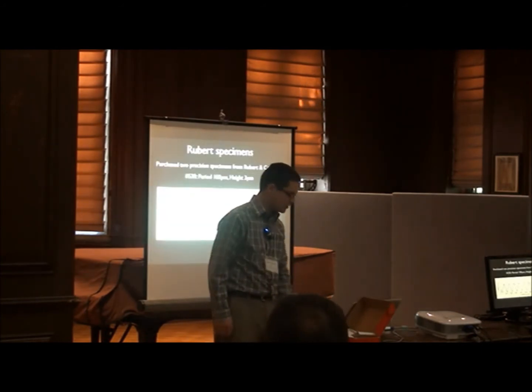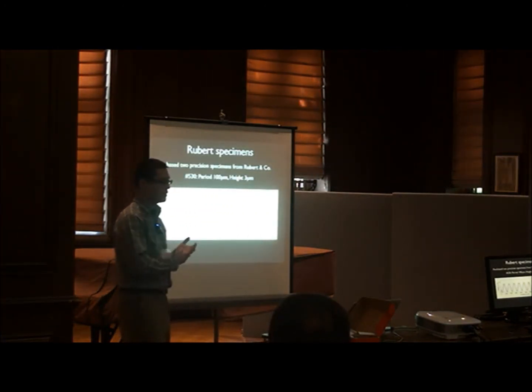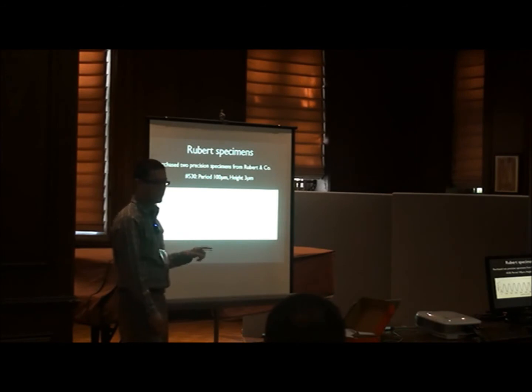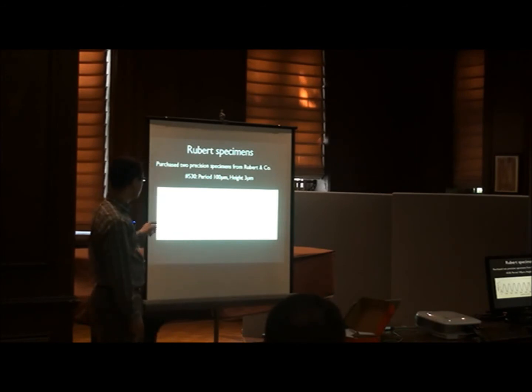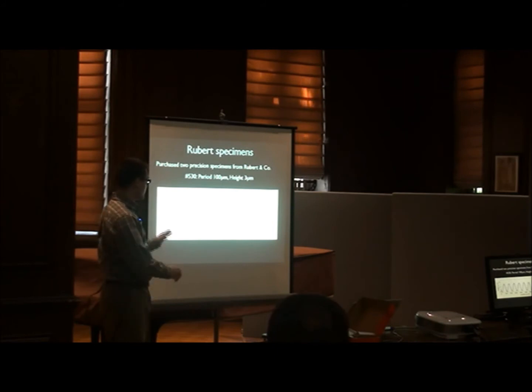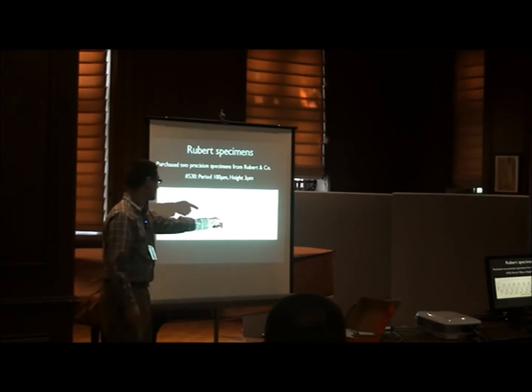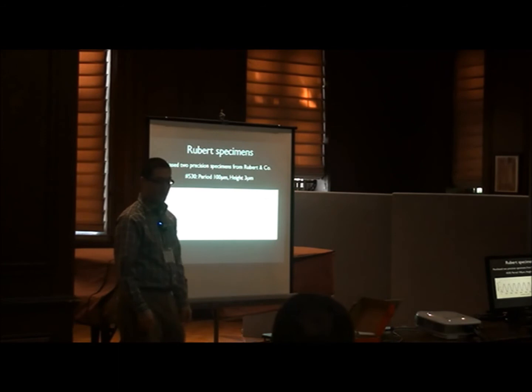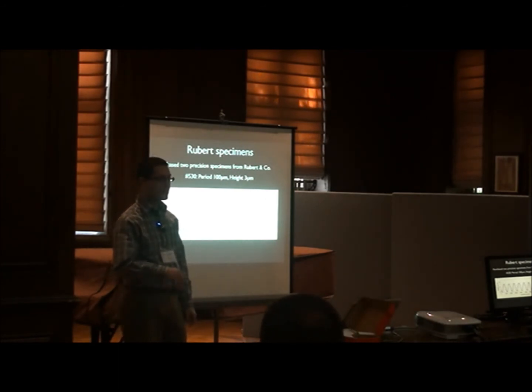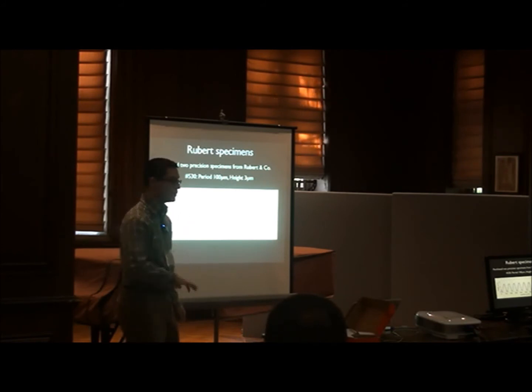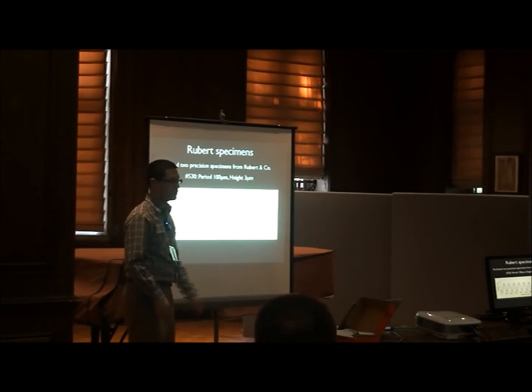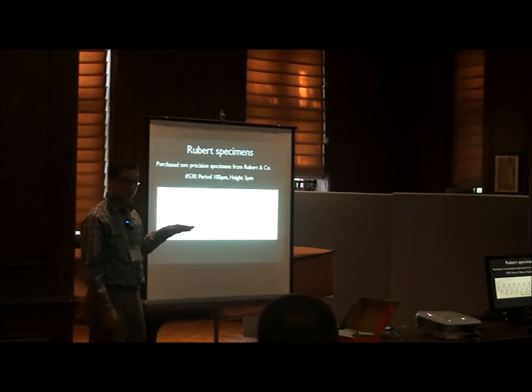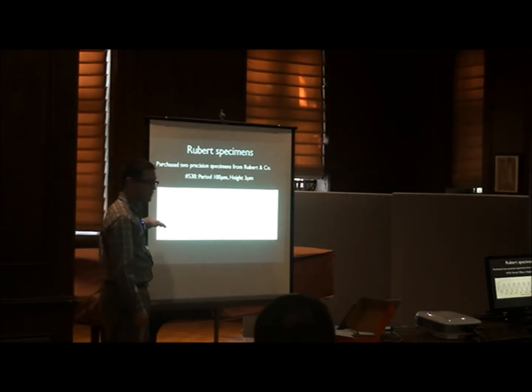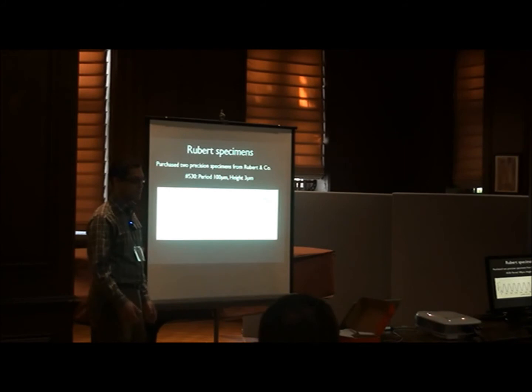Actually, let me skip this validation because I'll go into this one. This is a Rubert specimen. It's a periodic sinusoidal target, period of 100 microns and a height of 3 microns. So this is in fact compressed this way, this plot. We have 3 microns here on the y-axis and a millimeter across the x-axis. And this is what I was suggesting before, how the fact that we have local surface orientation measurements very finely spaced, and when we integrate them, we can get a smooth curve that shows submicron Z resolution. Because we're not stepping through Z to measure it, we're integrating lots of local orientation measurements.